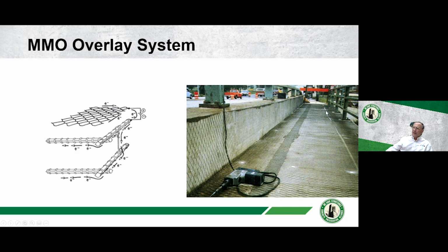And then they put the mesh down, and you put little plastic pins to anchor it to the surface, and you cut away around any of these metals. So here you see this is a guardrail foundation. This mesh should stay a good 2 to 3 inches away from any of these metals. A lot of times, people use 6 inches. So you just want to make sure that it's spaced out and there's no chance that this anode will contact that embedded metal. Otherwise, that'll create a short.